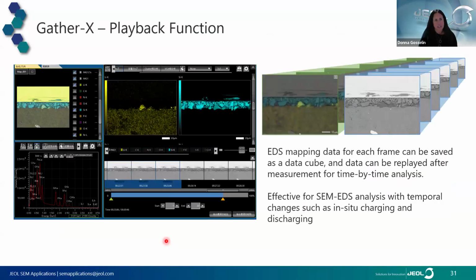And so we use GatherX to collect the EDS data. X-ray maps are collected during the charging and discharging. Our software not only collects EDS maps, but an image with each frame, and we have a playback analysis function so that we can view the full time domain of our experiment. So the data can be replayed after measurement, and we can even extract data from any portion of the time domain. This is very effective in observation of systems with different temporal changes, like this charging, discharging experiment.